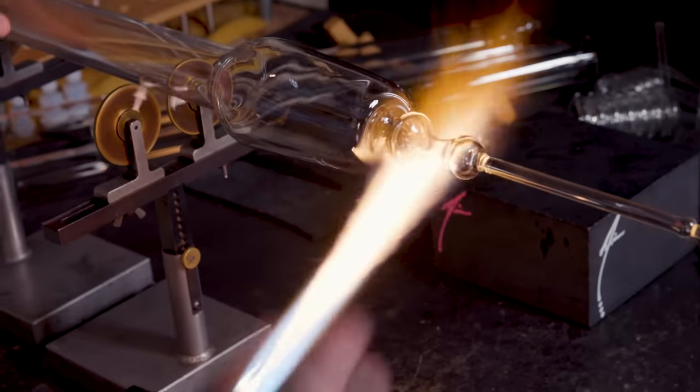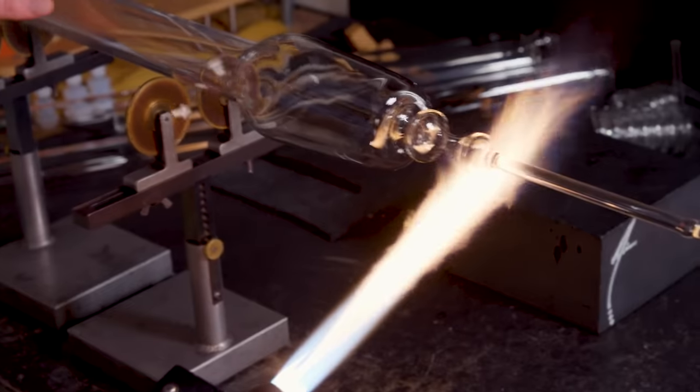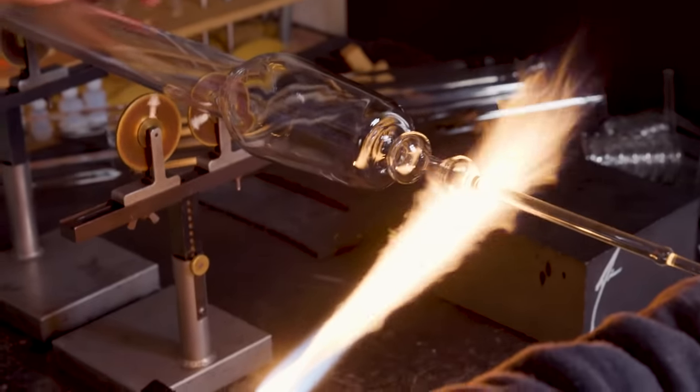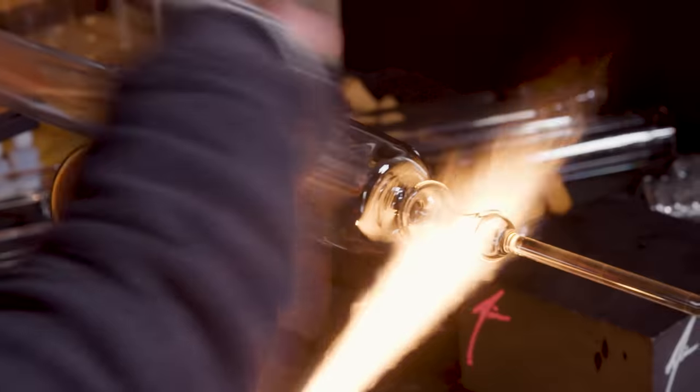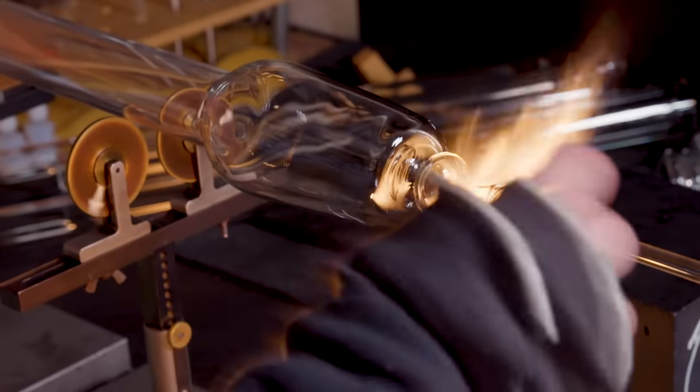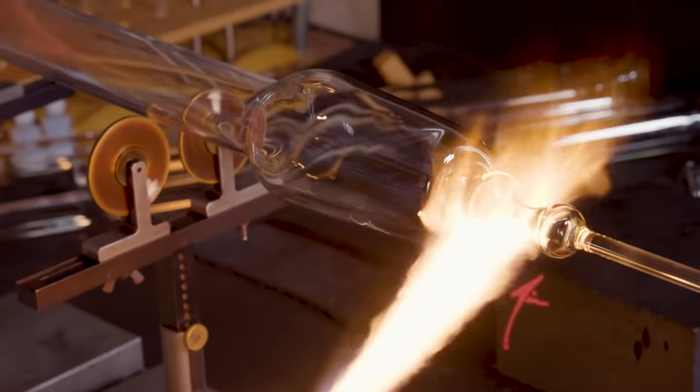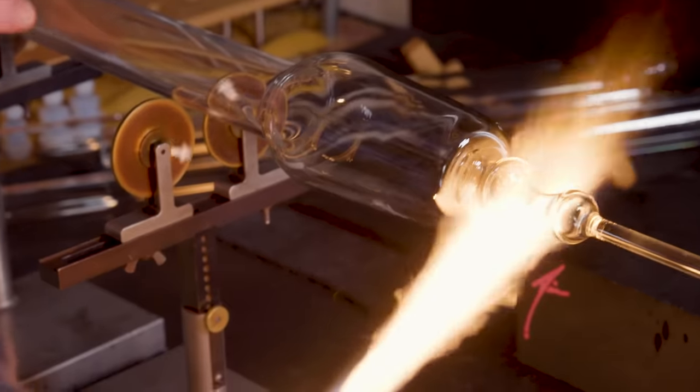Things have gotten kind of cool down here on the end. So I want to make sure that I'm not letting them get stone cold. It's a technique called flame annealing. I want to warm everything back up roughly the same temperature to help it equalize.